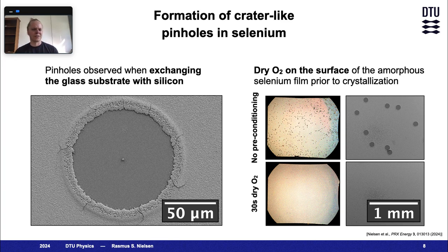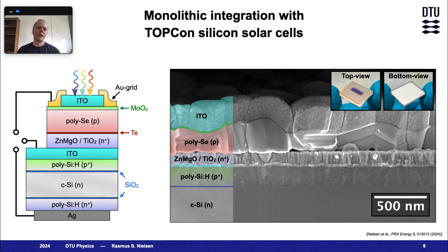We are not yet certain why this trick works so efficiently, and therefore also uncertain of the exact origin of the crater-like pinhole phenomena, but this just highlights how poorly understood the crystallization of selenium still is. In the end, we managed to transfer the single-junction device structure onto in-house fabricated TOPCon silicon solar cells with a few modifications to the process flow.